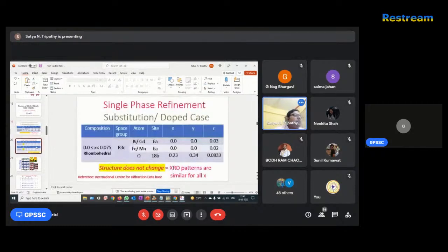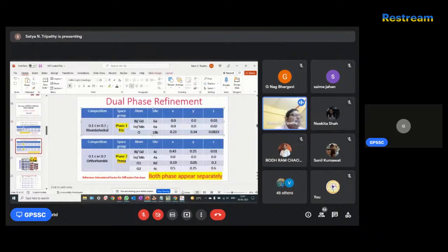So here you see that in the dual phase, from 0.1 to 0.2, I have used the R3C phase. In place of gadolinium, I have put bismuth. In place of iron, I have put manganese. So these are the atomic positions, right? Now, when you dope something, and that is evident from the new reflections, you basically use this one. This is gadolinium manganite atomic positions. You basically use the A site, because you don't know where the gadolinium will go. It may be bismuth, it may be gadolinium, so you have to give both probabilities. This structure is available for the rare earth manganites, yttrium manganite, gallium manganite, dysprosium manganite. All these structures have a PNMA kind of structure.